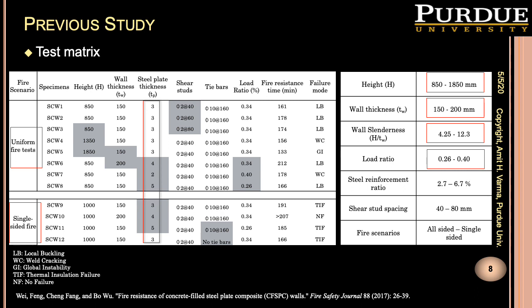This matrix also includes some of the failure modes that were observed for these particular tests, where the initial LB stands for local buckling, WC stands for weld cracking, GI, and there was only one specimen with GI that had global instability. There were some one-sided specimens that had thermal insulation failure, and there were some specimens that had no failure at all. The fire resistance time in minutes is reported in this particular column. What you'll notice is that most of these times are greater than 120 minutes, and some of them are even close to or greater than 180 minutes.